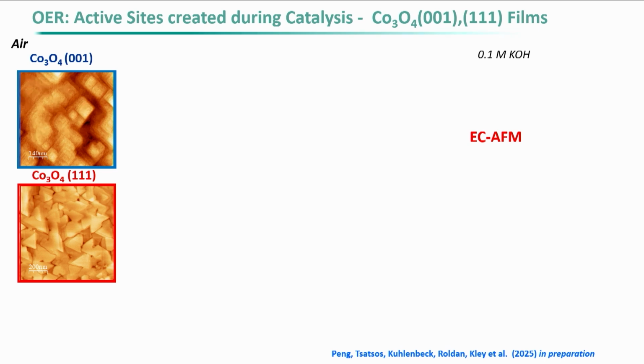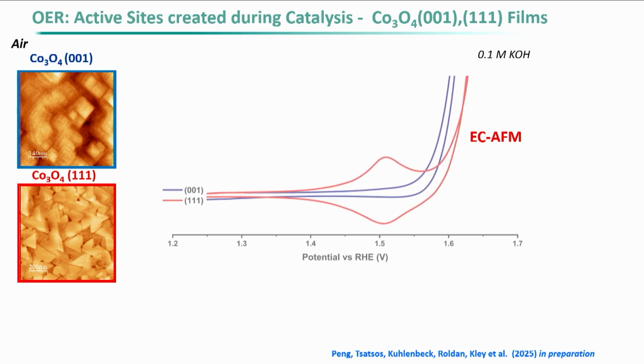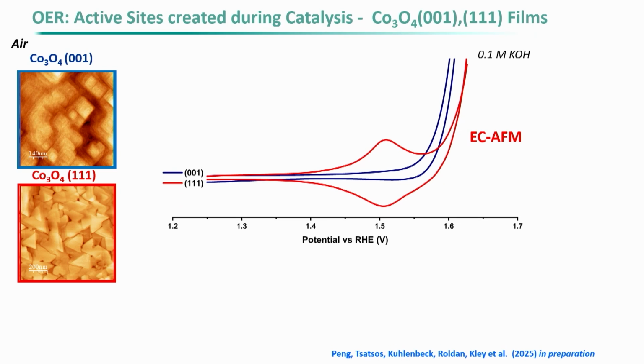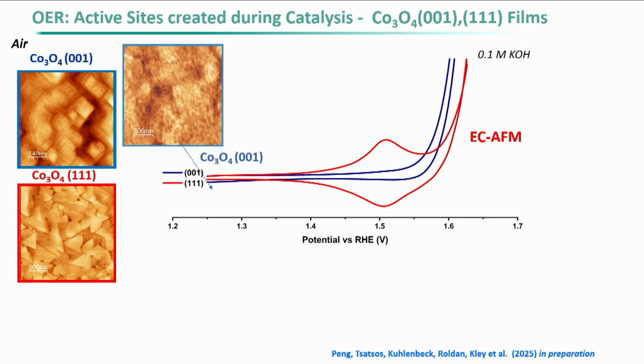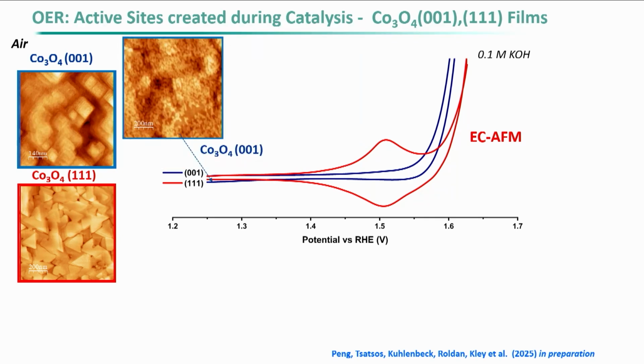And you have two different oxides. Only the surface orientation is changing, same film thickness, same material composition. And when you look at the electrocatalytic performance, it's different. This particular surface orientation works better than this one. Okay? This is very useful to know, and then we want to understand why this is, and we can look with atomic force microscopy at this material under potential control in the electrolyte, how it's changing.